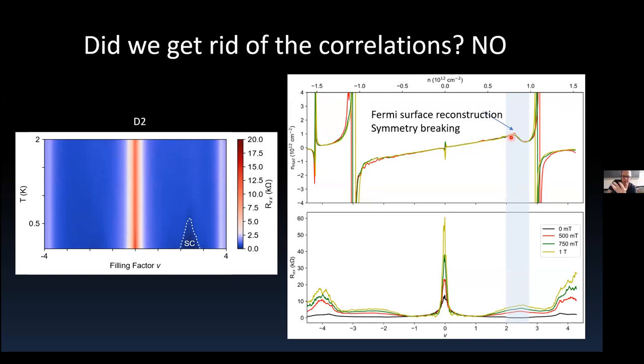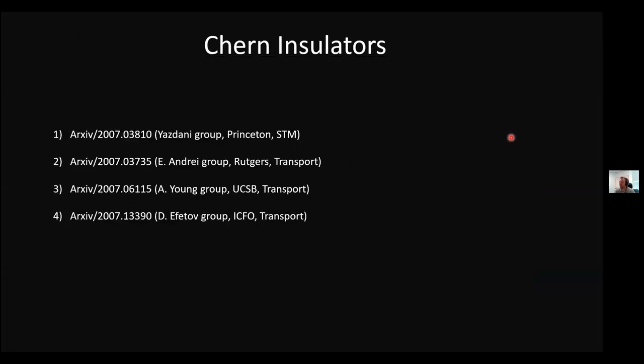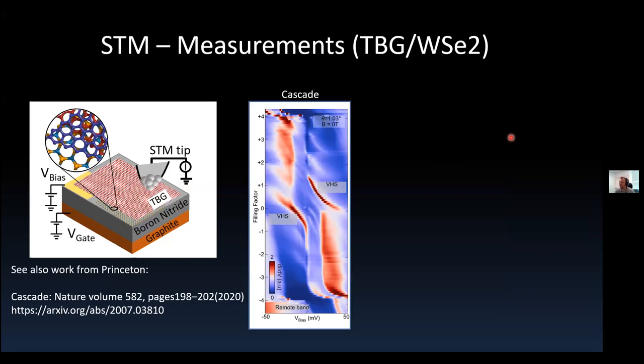Sorry, Stevan, I maybe missed it at the end, I apologize. Do you have an STM measurement of WSe2 supported? Oh yeah. Basically, I just left two slides. One is that we observe this cascade. This is just a spectroscopy at zero field, and we see the cascade that was reported in Ali's work from Princeton. For that, you need to have a certain sample quality to observe the splitting of these subbands. But what angle is this at? 1.03. No, but I mean around the 0.8. Yeah. 0.8.